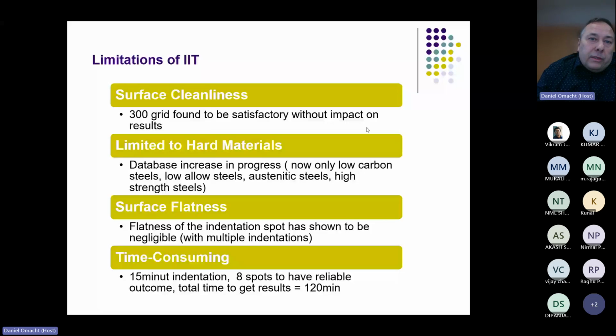The next limitation of instrumented indentation testing is surface flatness. In this way, I am speaking not so much about the surface flatness as about the perpendicularity of the indenter to the testing surface. It's necessary to have a perpendicular position, and a limitation can be the time, because each test can take from 7 up to 15 minutes. Plus, we have to calculate that in each place, we have to do about 7 tests. So together, we are speaking about 1 or 2 hours for one test.